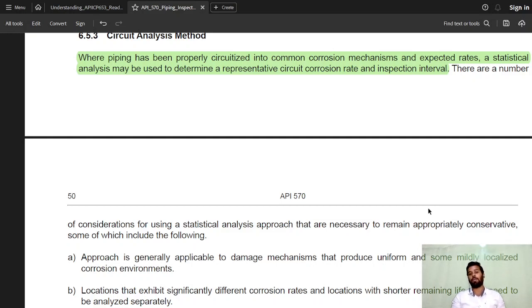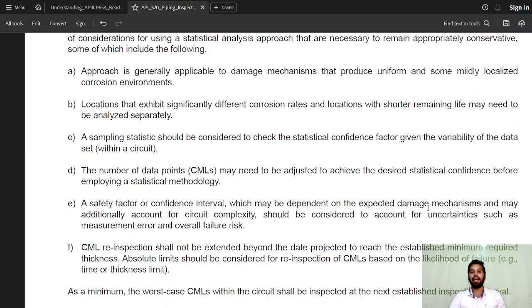For piping that is properly circuitized into common corrosion mechanisms and expected rates, a statistical analysis may be used to determine the representative circuit corrosion rate and inspection interval. There are a number of considerations for a statistical analysis approach that are necessary to remain appropriately conservative. Some of them include: the approach is generally applicable to damage mechanisms that are uniform and some mildly localized corrosion. Locations that exhibit significantly different corrosion rates, and locations with shorter remaining life, may need to be analyzed separately. Sampling statistics should be considered to check the statistical confidence factor given the variability of the dataset.